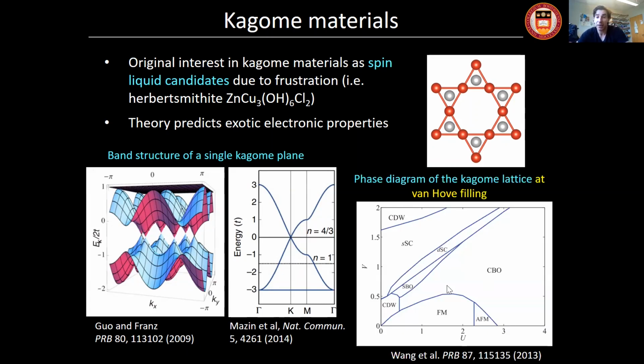Another theoretical prediction that was particularly nice is what happens if you tune the filling to the Van Hove singularity. The Van Hove singularity, kind of like the flat band, also has a lot of localized states. Depending on the interaction and the repulsion strength, you can actually get different phases. So not just magnetism, which is these two below, but you can also get different charge density waves, bond ordering, interesting superconductivity states, and so on.